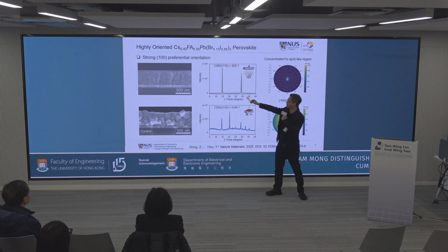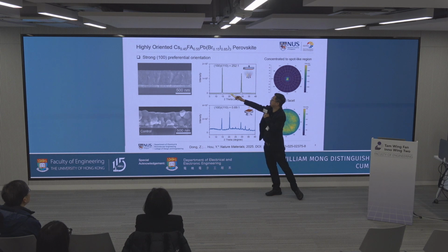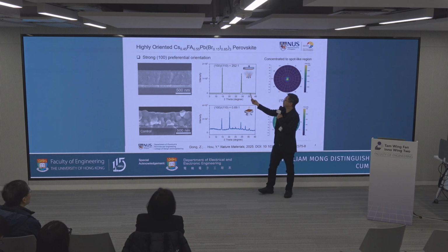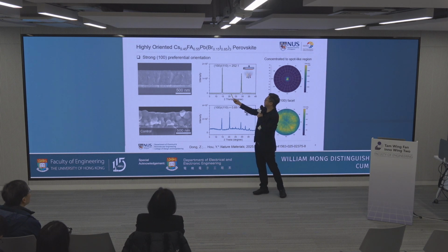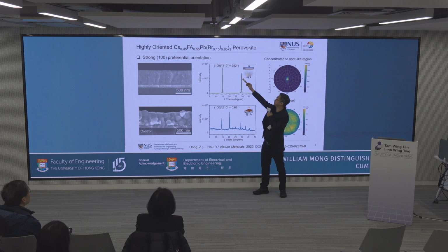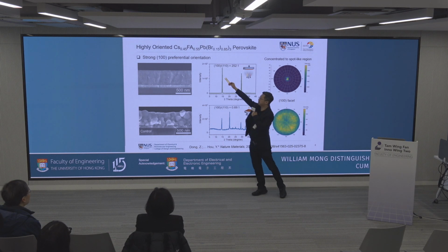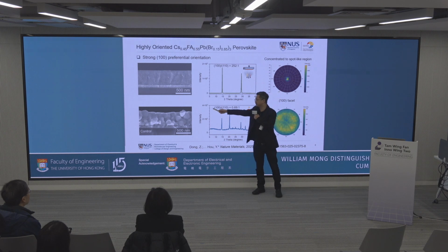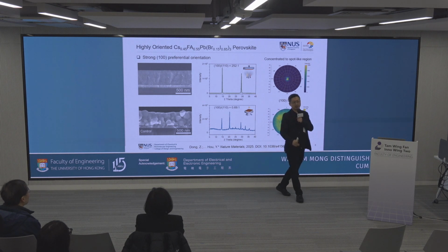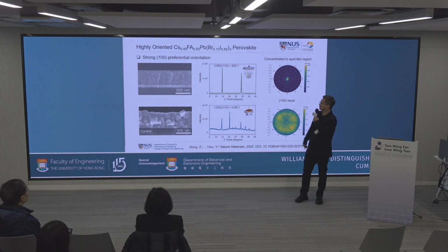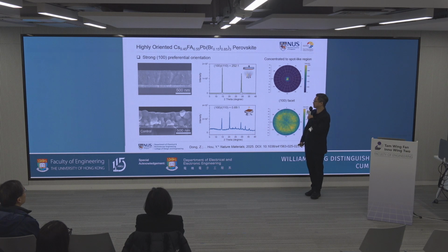And all you can see is the 100 and the 200 orientation. And the 110 is very, very small. So if you look at the ratio, it is 252 to 1. And if you look at the XRD intensity, it is 10 to 5, and the control normally is like 10 to 3. So the enhancement of this peak intensity is now 2 orders of magnitude. It's 2 orders of magnitude better.